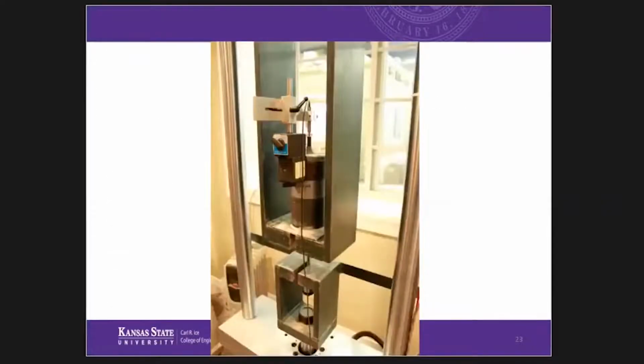The pullout test: we place the indented wire concentrically in a 4-inch diameter steel can with a special mortar mixture that uses an Ottawa sand and predefined concrete mixture components. We then pull that wire at a rate of 2,000 pounds a minute until we have a slip of 1/10 of an inch at the top of the member.